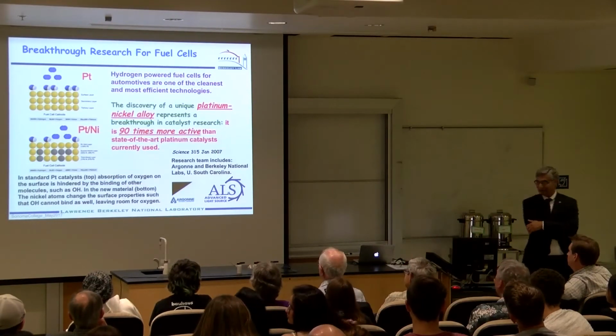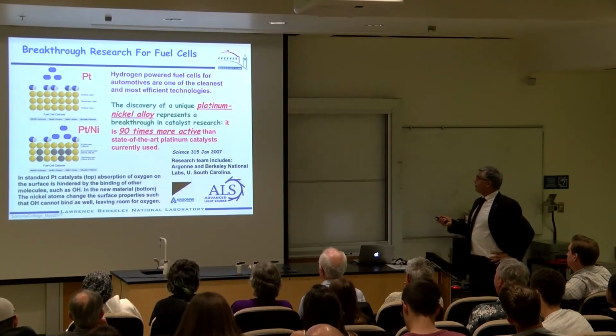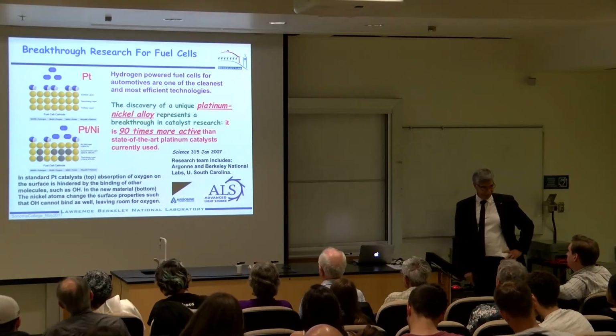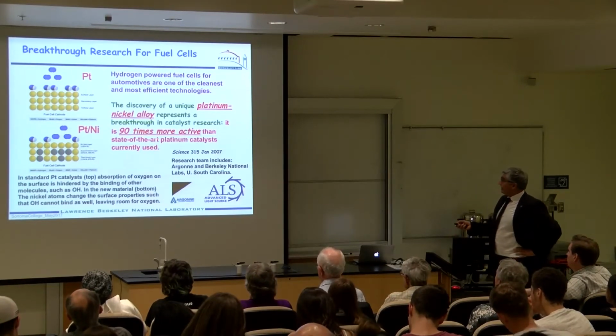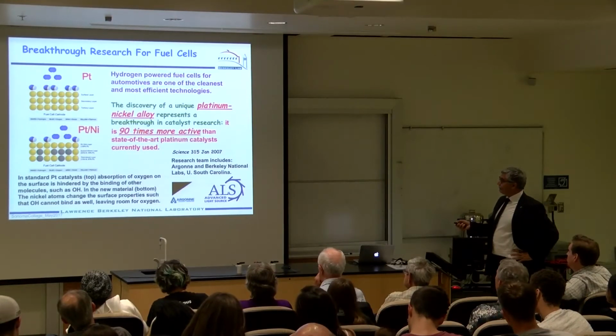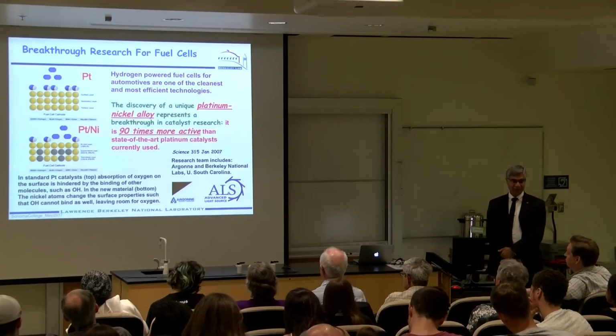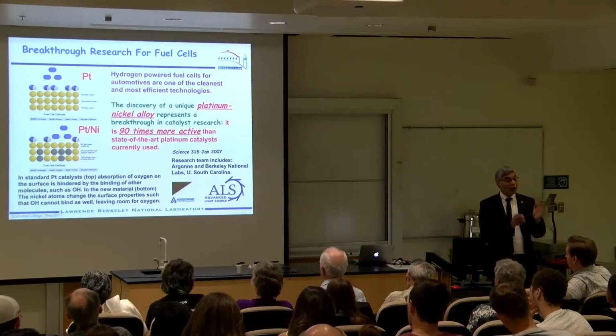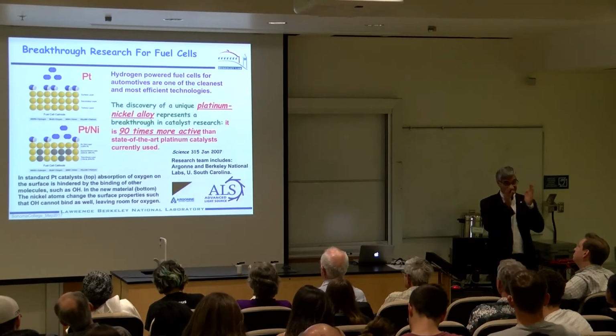So this is the outcome. One of the research efforts asked: why don't we combine platinum with nickel? The outcome of that research was that they were able to make platinum and nickel act as an electrode 90 times more active than the state-of-the-art platinum catalyst. So 2 orders of magnitude gain is an extremely good gain. Why did that happen? It is spectroscopy. I haven't shown the spectra, but I will show you the physics of what went in.